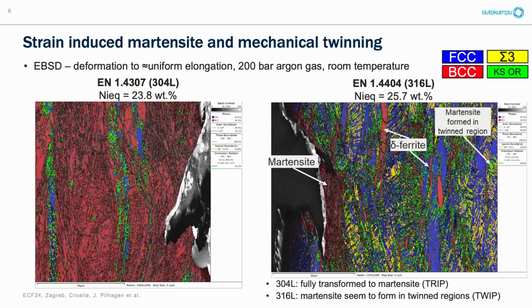But if you look at the 316, you can see that if you ignore this kind of martensite region at the crack, it mostly consists of this blue and yellow color. The yellow indicates regions where you have mechanical twinning, and the green is where you have started to have martensite transformation. So at uniform elongation, the 304 is fully transformed to martensite, which is the TRIP effect, where TRIP stands for transformation-induced plasticity. And for the 316, it seems like first you have mechanical twinning, and then you have martensite nucleated on these twinned regions.